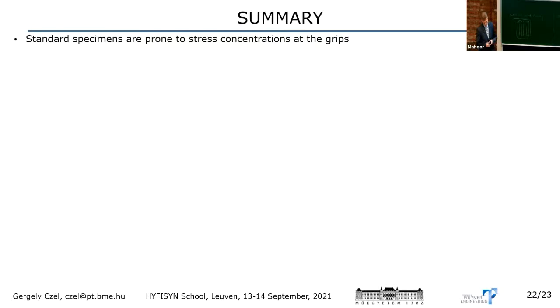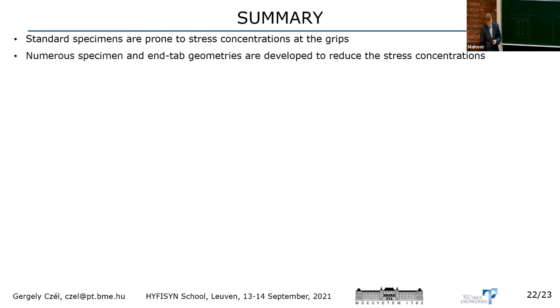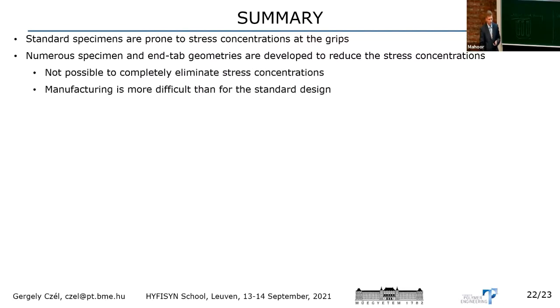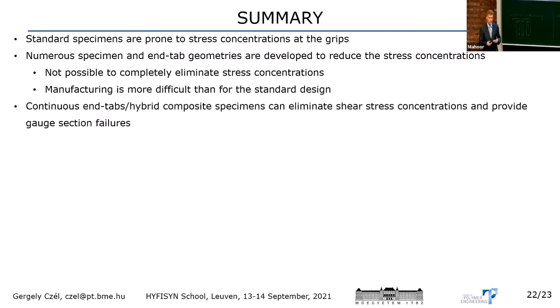And yeah, a few key points as a summary. So the standard specimens are, yes, prone to stress concentrations, and there are different ways of trying to reduce this, but it's not possible to completely eliminate the stress concentrations by simply redesigning the tabs or the specimens. And usually doing this, it brings some extra complication into our preparation processes. On the other hand, continuous end tabs can fully eliminate the shear stress concentrations and provide consistent gauge section failures.